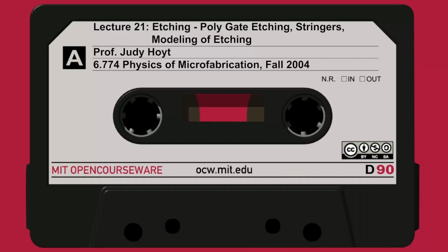Okay. Now, step B here, I put it into the etcher, and I use the photoresist as a mask to etch the poly. So this looks good. I have very nice sidewalls, and I stop on the oxide. But what happens? Well, in this region right here, look at the thickness of this gate material where it goes over the step. The thickness from this point of the top to the very bottom is almost twice what the thickness is in the flat region.